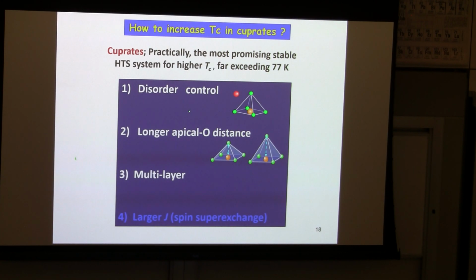I have thought about various ways to enhance the Tc of cuprate. One way is to control disorder. As you may know, the cuprate is basically a disordered crystal. So if we can reduce disorder as much as possible, we expect that Tc goes up. Unfortunately, there are only some results. For example, you may know the bismuth-based cuprate, which is normally a 90K superconductor. In this case, by reducing disorder in the bismuth-based cuprate, I could increase Tc from 90 to 98K.